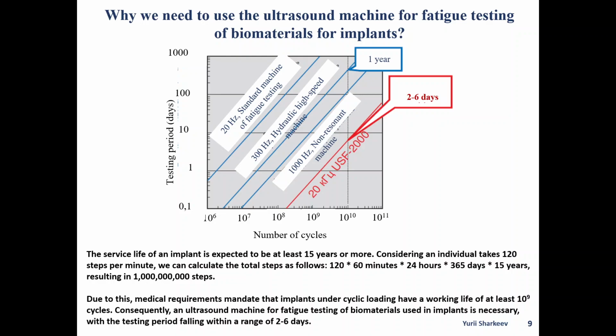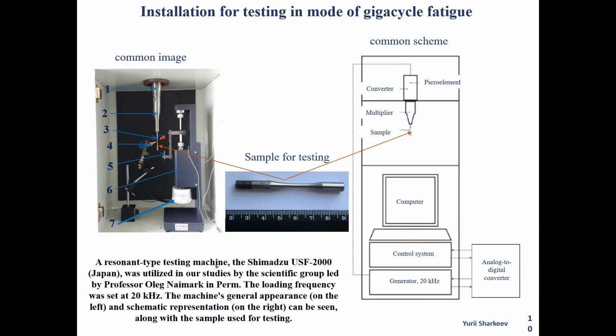Consequently, an ultrasound machine for fatigue testing of biomaterials used in implants is necessary, with the testing period falling within a range of 2 to 6 days. A resonant type testing machine, the Shimadzu USF 2000, was utilized in our studies by the scientific group led by Professor Oleg Naimark in Perm. The loading frequency was set to 20 kHz.